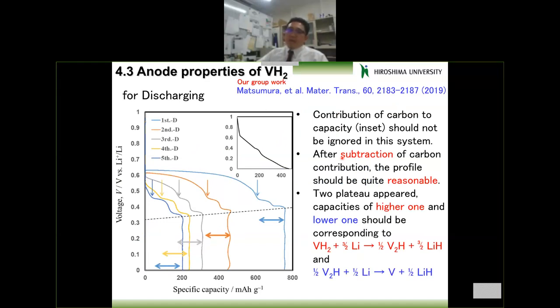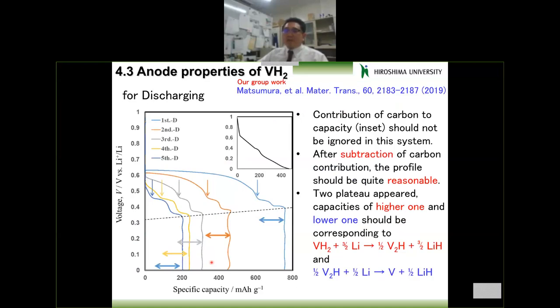We assume a hard carbon profile, something like this, and then subtract it from these profiles. In this case, we can get quite a clear result corresponding to the vanadium charge discharging properties.